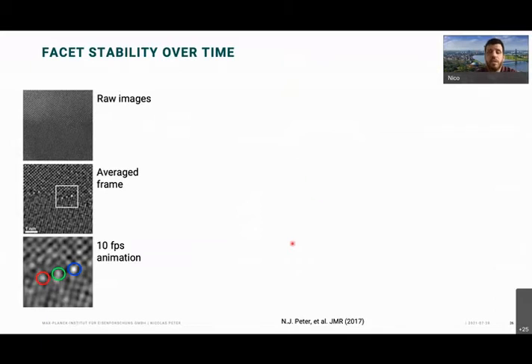So finally, I would like to also go a little bit more into detail on how the silver containing segment looks like. And for this, we did some in situ work at the STEM, where we acquired 200 raw images, which are shown here, so you cannot see much. We averaged then 4 of them to get a little bit more the feeling of how things are related to the image. And you can see already here again the bright columns. And then we zoom into these and make an animation out of that.